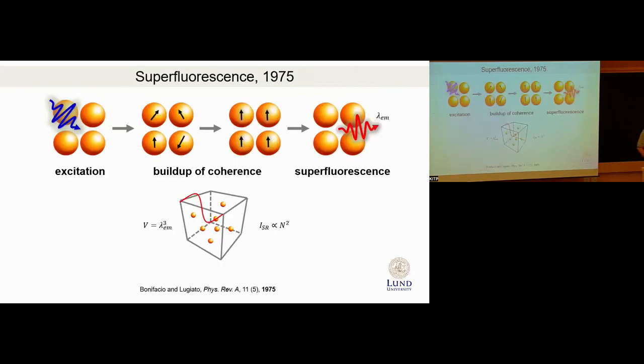Next, in '75, two theorists from Italy, Bonifacio and Lugiato, said, wait a second, it's not Dicke superradiance. Actually, what you saw was superfluorescence. And what was the difference? The difference was that they added this step of build-up of coherence. What happened is that you excited your molecules, but at the beginning there was no coherence. Each excited molecule needed some time to couple to the field and then essentially perform a phase transition into the macroscopic coherent state, from which the emission happened. So they added this step, also treated it for inhomogeneous broadening, and then called it superfluorescence. This is where I believe superfluorescence actually takes its name.